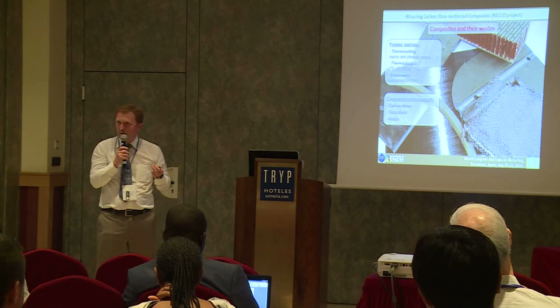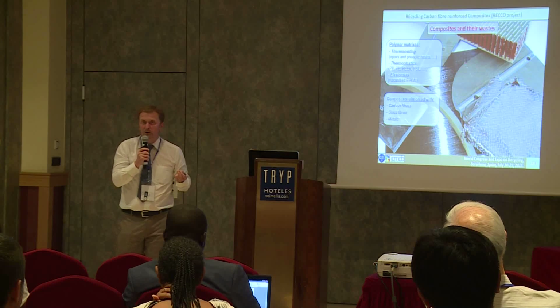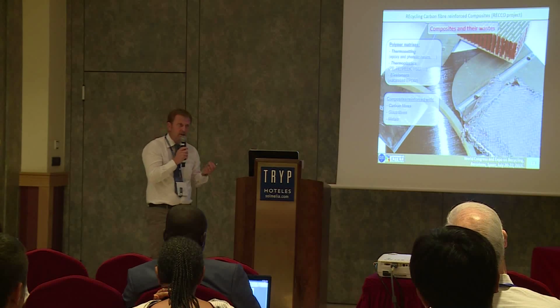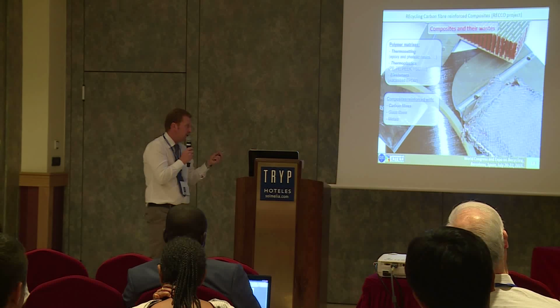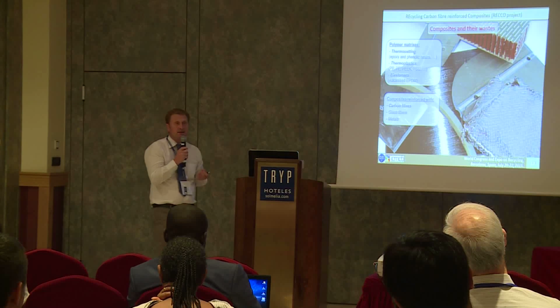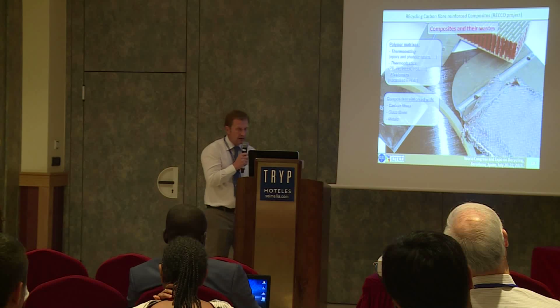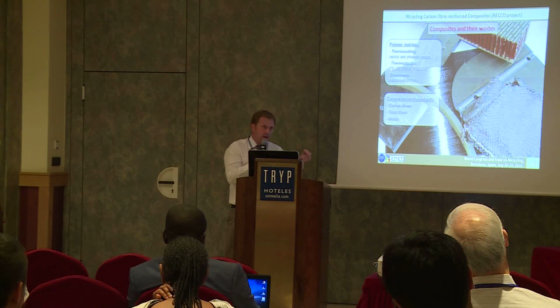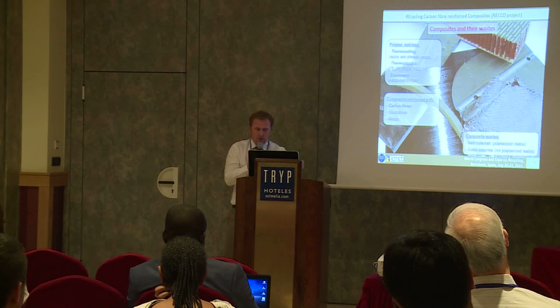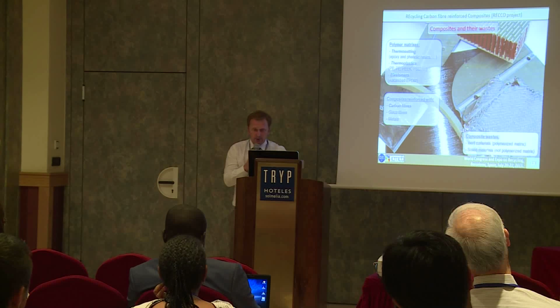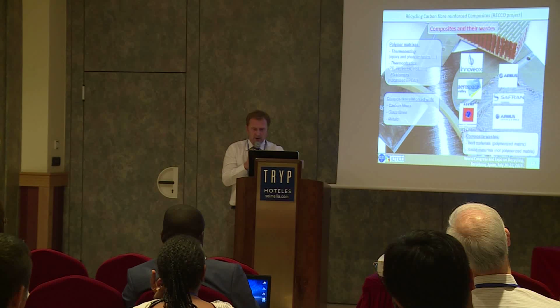Regarding the reinforcement, we focus on carbon fiber because, at that time, it could work with glass fiber, but from an economical point of view, we cannot believe that this kind of innovative technology can be economically self-sufficient if you recover glass fiber. But from a technical point of view, I would say it works. For the polymer, it can be inert materials with a polymerized matrix or not polymerized matrix.